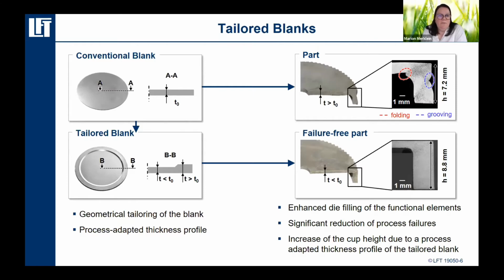And you can see here on the left the first example of such a tailored blank, where we increased the sheet thickness locally also in a rolling process. In this case, it is a mixture between a conventional rolling process and a ring rolling process. And doing so, we were able to increase the sheet thickness of the material where we need the material. And in the comparison on the right, you can see if we use the conventional sheet, we have the problem of the grooving and folding. And if we use such a tailor rolled blank, we can see that the increase of the sheet thickness will lead to an increase of the stiffness. And so we are able to avoid the failures we saw before.